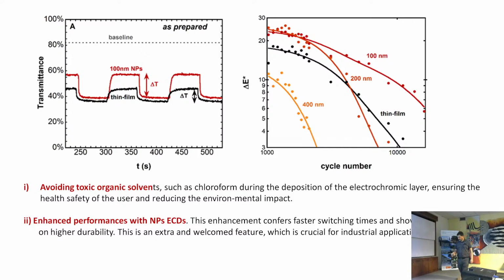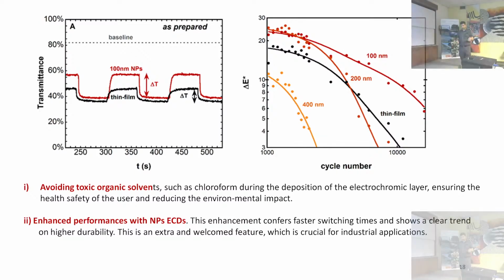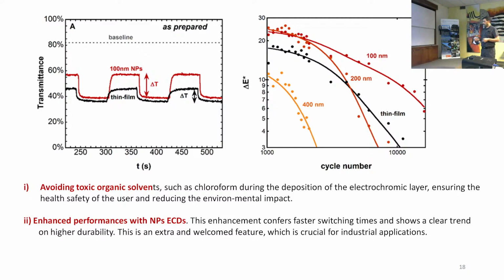We analyze this, and not only the color contrast is bigger, but also the switching times are smaller, so the device is faster, and most importantly, the durability of the device increases a lot when you go from thin film to nanoparticles of 100 nanometers. Then if you increase the nanoparticle size, then the durability decreases again. Okay? So we have a neat point with 100 nanometers particle size in which not only we are using water instead of organic solvents to make the deposition, but also the device works better.